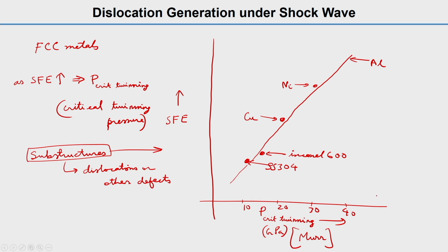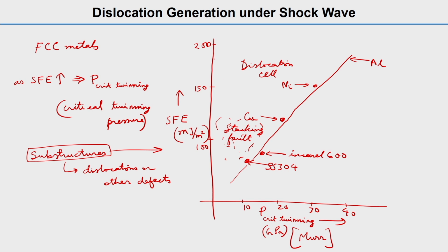And here also, the unit of this stacking fault energy will be millijoule per meter square. So, it is like 100, 150, 200, something like this. What we need to understand here, and why we are drawing this, is that around this area, this will be stacking fault, and if you go higher here, this will be dislocation cell. That means if you have a high stacking fault energy, the dislocation cell will be generated.